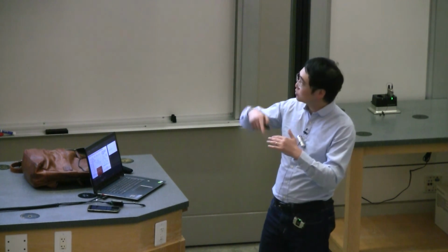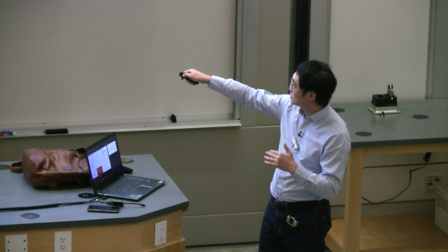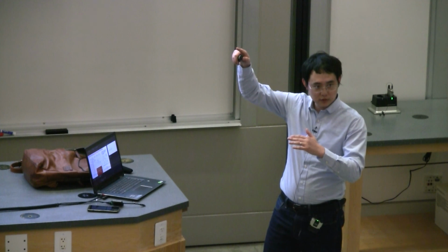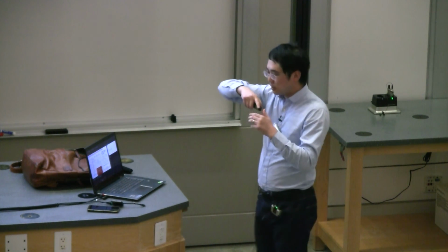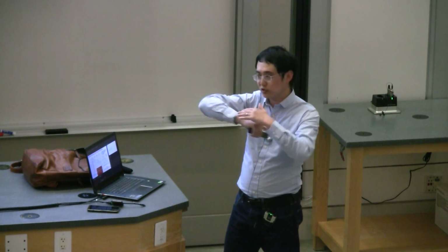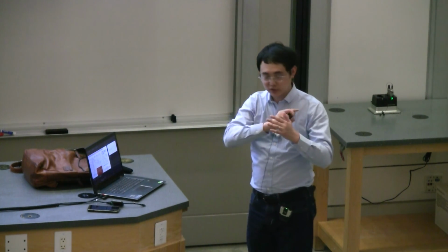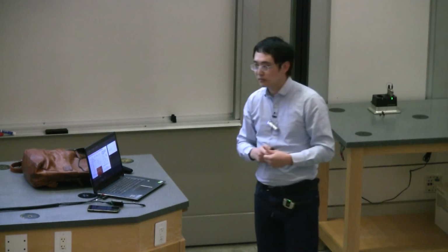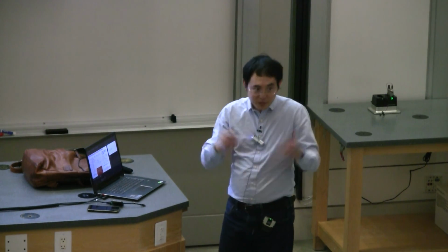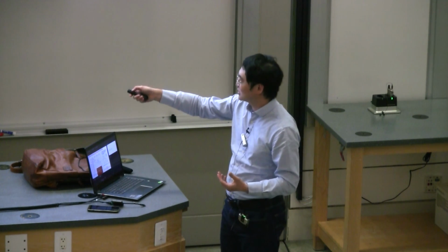From 300 millikelvin to 1 Kelvin, the RXX value in the states will increase. And 1 Kelvin is roughly where you lose the time reversal symmetry breaking, and the anomalous Hall is just gone. Yeah. So I'm not particularly bothered by the fact it's not touching 0 yet.